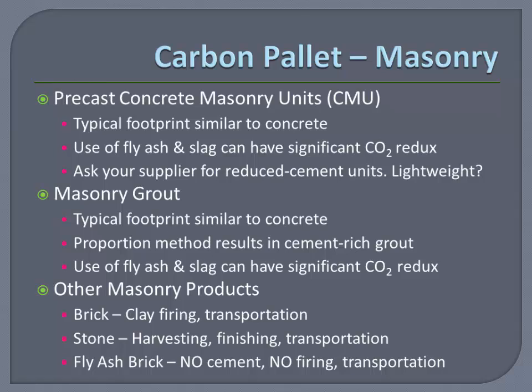And I'm from upstate, and what I've learned in upstate, and it's probably true of most of the rest of the country, is that if you ask your block producer to provide a low cement block, they will. They can usually reduce the amount of cement that they would have otherwise used by about 25 or 30% by using fly ash and slag and other things and just optimizing the mix design. But you have to ask. That frequently is at no additional cost. So if you want carbon reductions for your block, ask for carbon reductions and you'll probably get it.